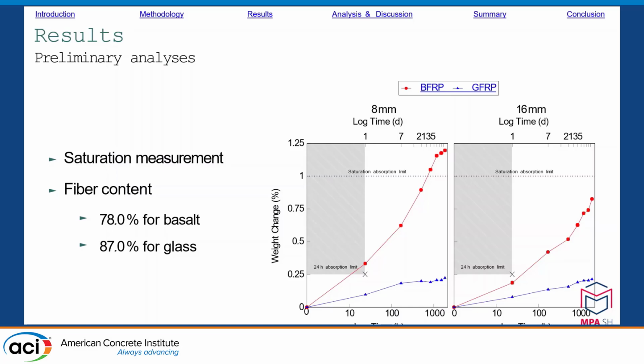The fiber content of the rods was also examined. The investigation showed that the basalt rods had a fiber content of 78% and the glass fiber rods of 87%.